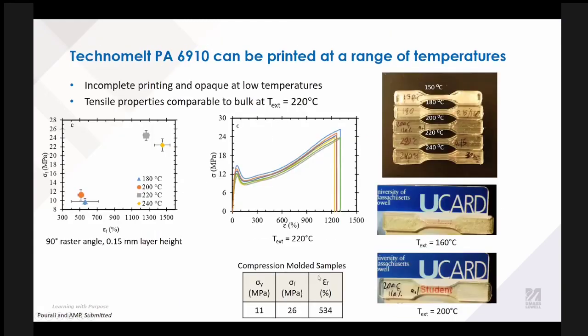What we found is that this particular hot melt adhesive can be printed at a range of temperatures. We can print structures ranging from 150 to 240 degrees Celsius. That said, we found that we get the best properties at 220 or higher. And actually, the mechanical properties of the samples at 220 or higher are comparable to compression molded samples, so traditionally manufactured samples.